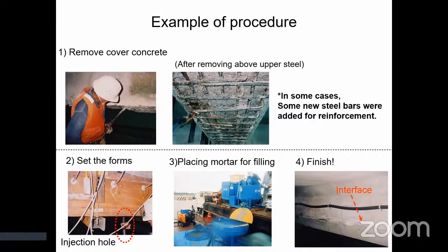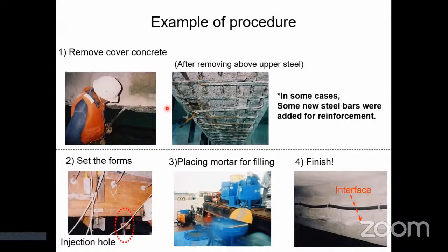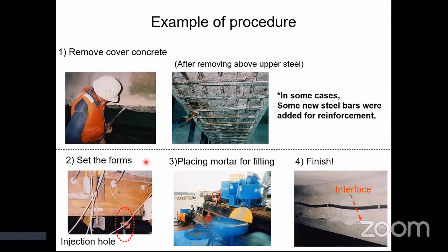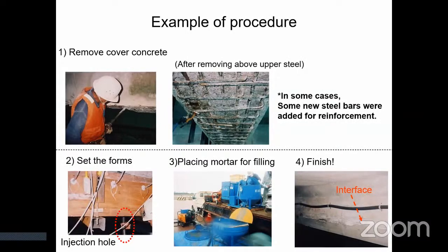This slide shows one example of procedure of cross-sectional repair. First phase, remove the cover concrete. Here, deteriorated concrete should be removed above upper steel. Also, in some cases, some new steel bars are added for reinforcement. Second phase, set the form. Third phase, place mortar for filling and finish. Also, this is the interface between new mortar and original concrete.